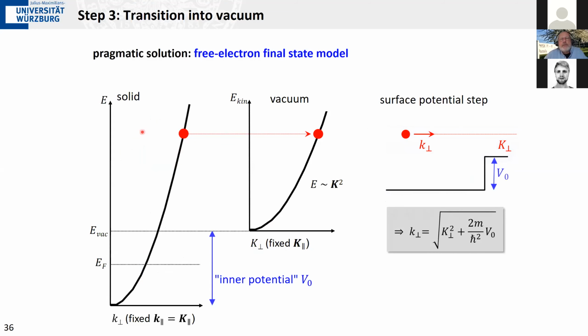Or you assume that way above the Fermi level, way above the vacuum energy, the electrons do not experience the crystalline potential so strongly, and you can replace the true band structure by an approximate free electron parabola, which, however, has a bottom different from the vacuum case, namely here somewhere where you have the bottom of your valence band. It's like assuming that rather than a periodic potential here, you have just a simple potential step from the interior to the vacuum, and the step height is often called the inner potential.